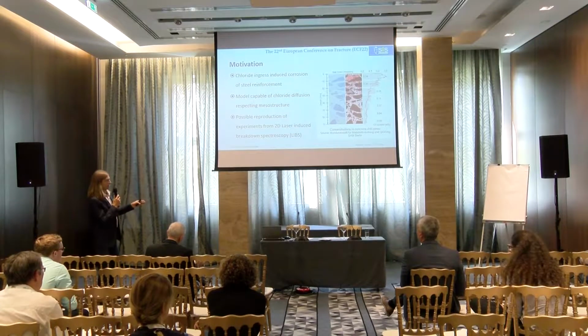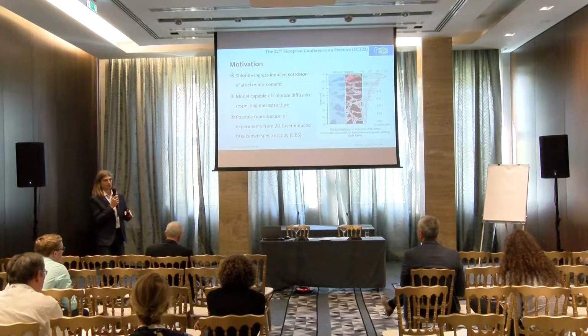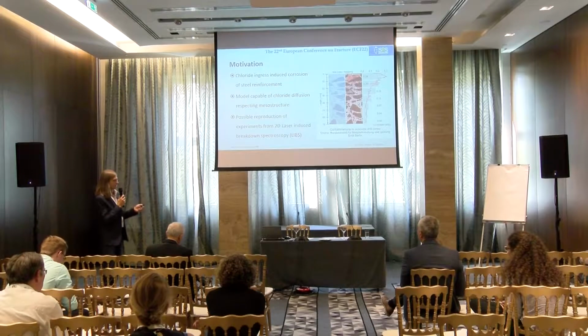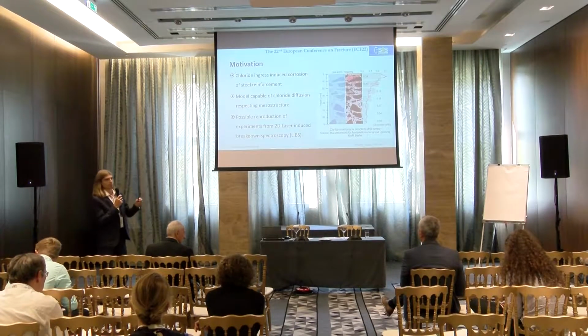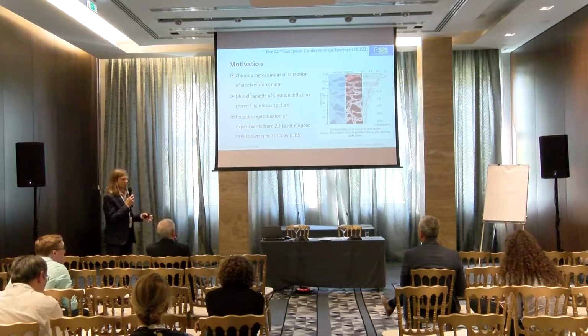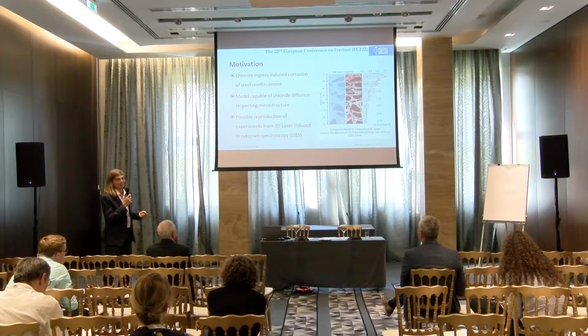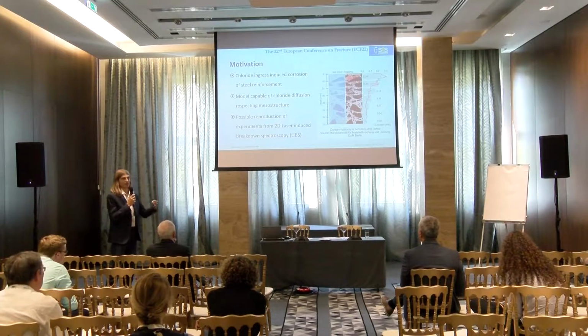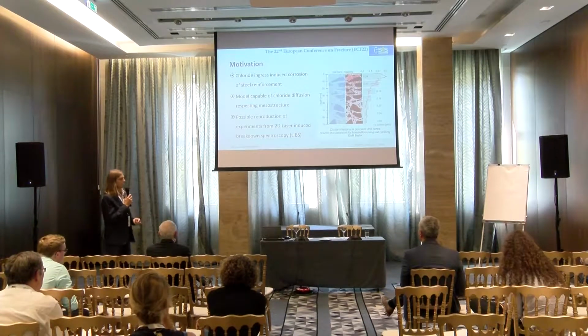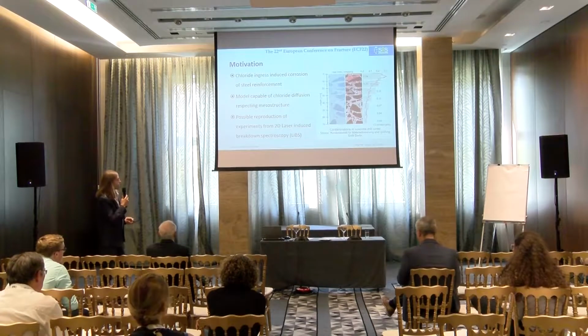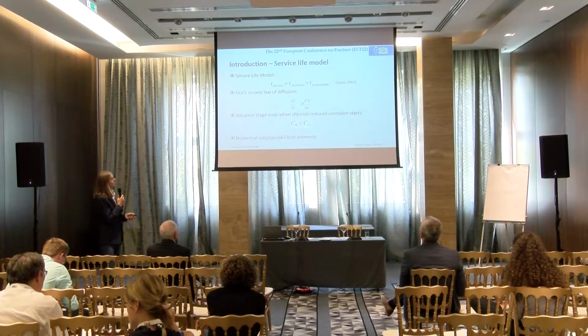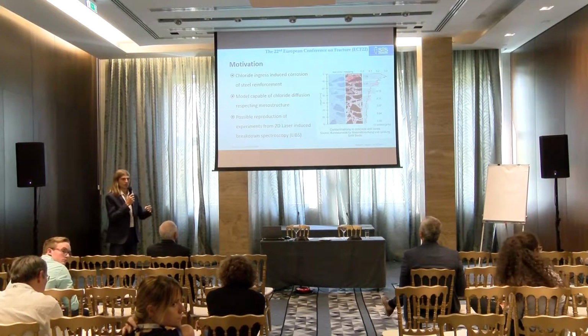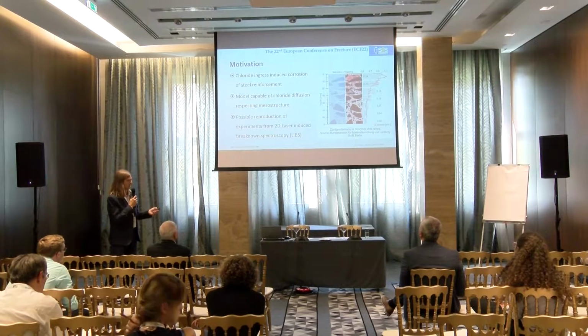And this contribution is not oriented on the experiments, it's oriented rather on the testing of the modeling. We are not possessing that capability. We are using the drilling and making a powder and then a chemical analysis, which is quite time-consuming, and you don't have this heterogeneous properties over the 2D profile. However, in case in some future time we will have the ability to have the scan like this, it would be nice to have the model that can be capable of reproducing the physical experiment. So we were trying to evaluate the possibility of the application of the probabilistic random fields to model the heterogeneity.